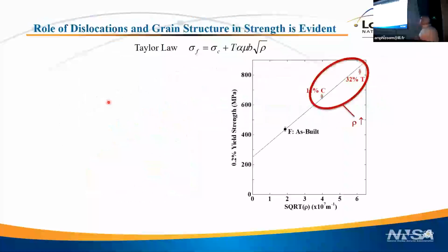So we made this battery of samples, and then we go back and test them and can relate them to the flow strength. So the orange is the raw material. That's just sort of there for comparison. But you start up in the gray is the as-built, and my laser pointer is getting very slow. In the as-built material, and each heat treatment step reduces that flow strength. So the natural thing to do then is make what's called a Taylor plot, which plots the yield strength versus the square root of the dislocation density.